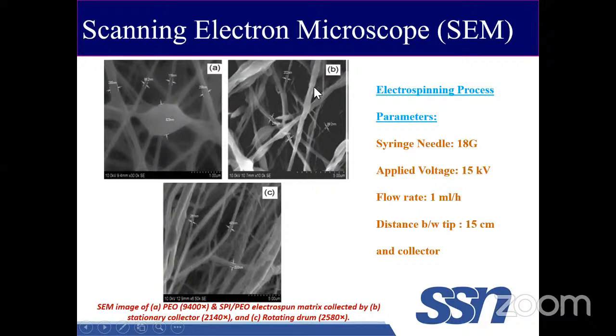Biologically, we have an advantage with this rough surface because cells will adhere more to the rough surface than the smooth surface. So we took these samples for further analysis. The electrospinning process parameters that we utilized to prepare these nanofibers are: a syringe needle size of 18 gauge, an applied voltage of 15 kV, a flow rate of about 1 ml per hour, and a tip-to-collector distance of 15 centimeters.